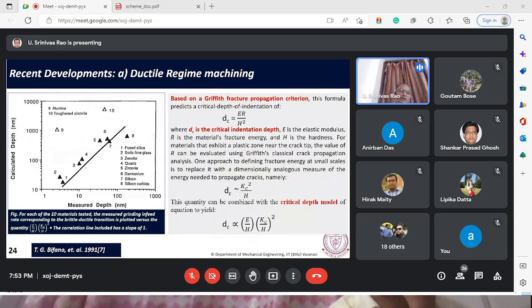So similarly, some other investigations have been done. In all these cases, the calculated indentation depth is related to the fracture propagation criteria, and through that the critical depth is obtained.